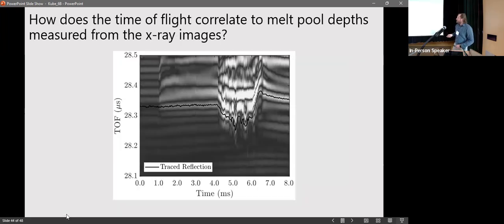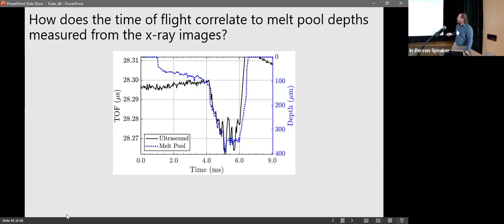One of the things we did was simply trace the time of flight, or the arrival time of the first echo, and we compared that to the melt pool depth that we obtained from the X-ray images. And so we get a very strong correlation between the melt pool depth and the time of flight, including some of the dynamic information that's happening. So how that keyhole is fluctuating in time. Then obviously we have solidification information, so the solidification rate here is on the order of about 1 millisecond.